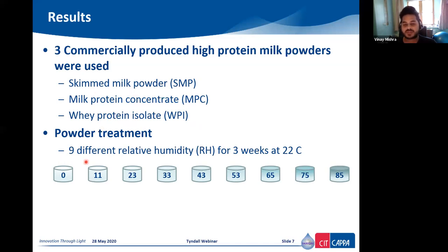I placed them for 3 weeks at 22 degrees Celsius at 9 different relative humidities, ranging from 0 to 85. And you can calculate that I ended up having 27 samples to image with AFM. Now, moving on to some of my results.